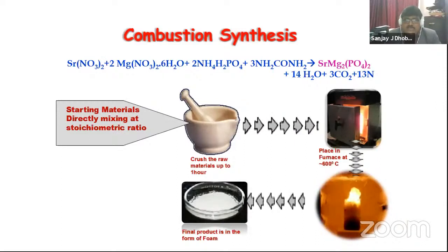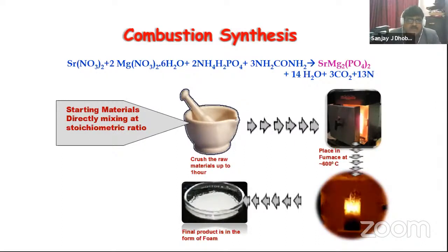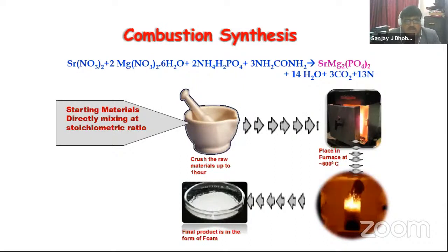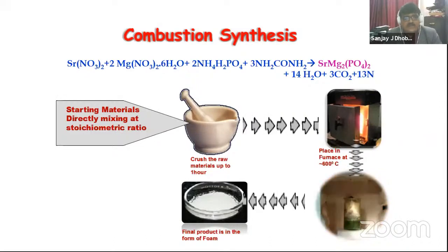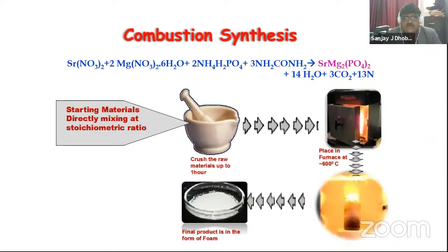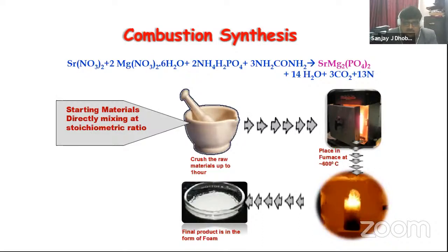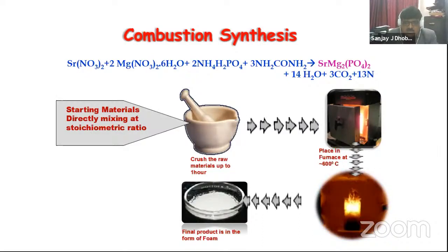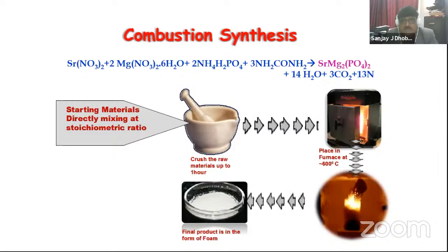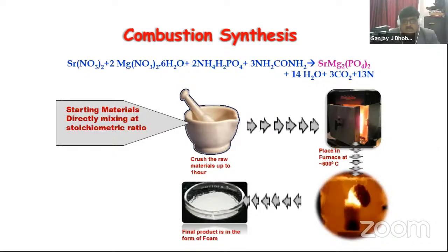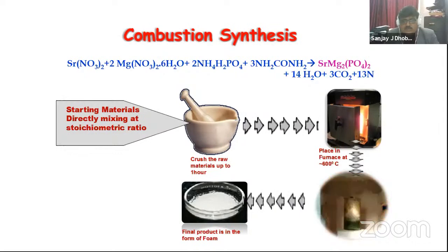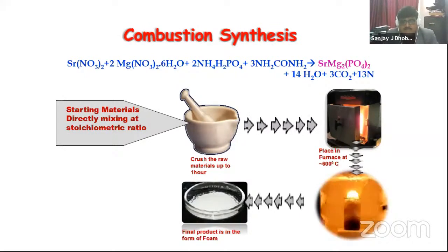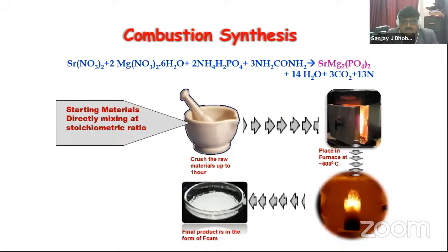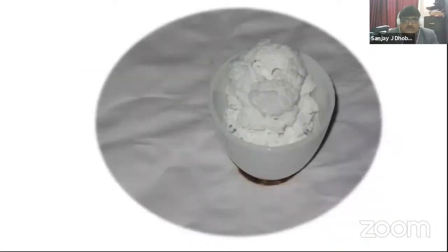One of the compounds, SrMg2(PO4)2, is prepared from strontium nitrate, magnesium nitrate and ammonium dihydrogen phosphate. In this method, the starting materials are used only in nitrate form. Then the material is prepared by this process, and the temperature of this flame is 1600 degrees centigrade. You can see here this is the flame. If you observe this flame, then your material is 100% prepared. You can crush it, and then nanoparticles are possible here.